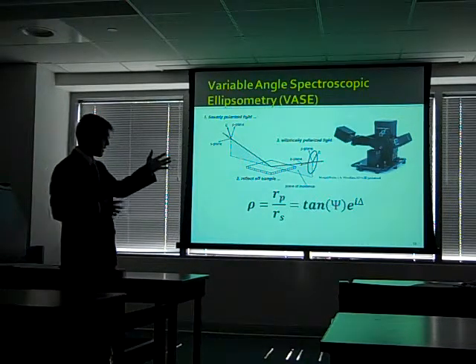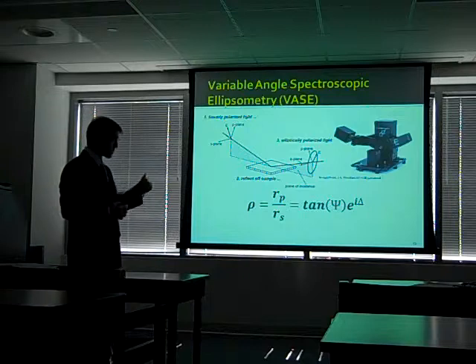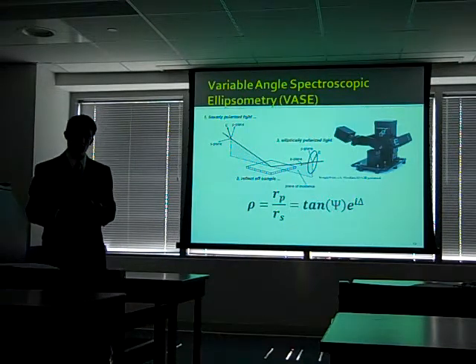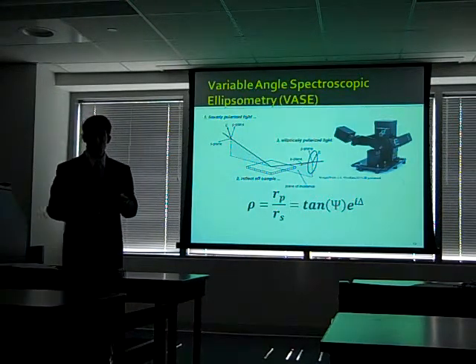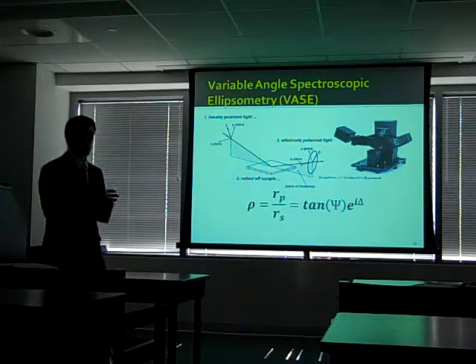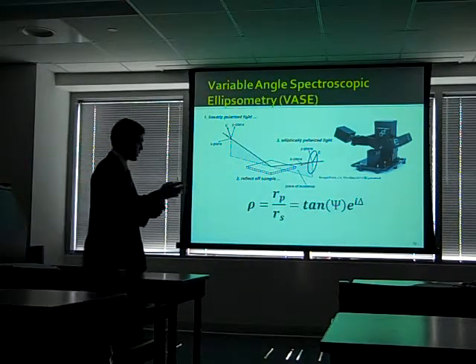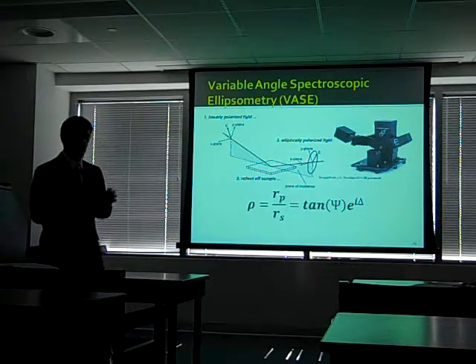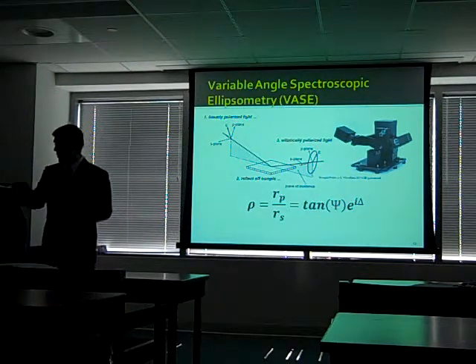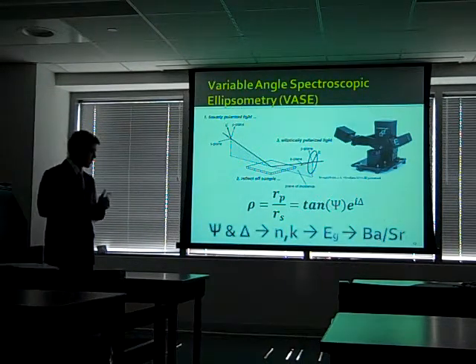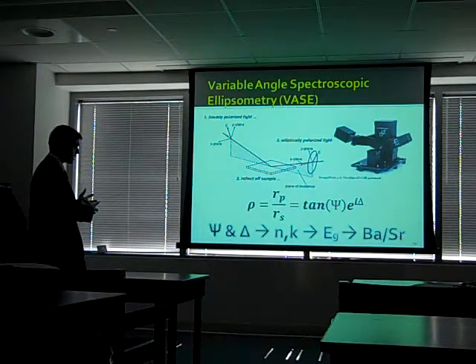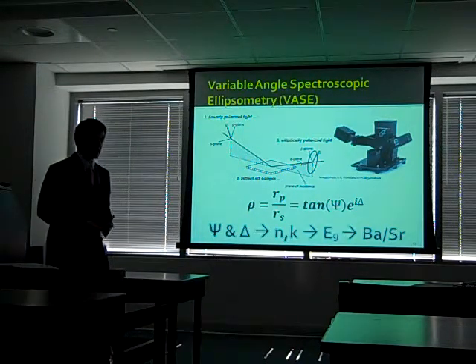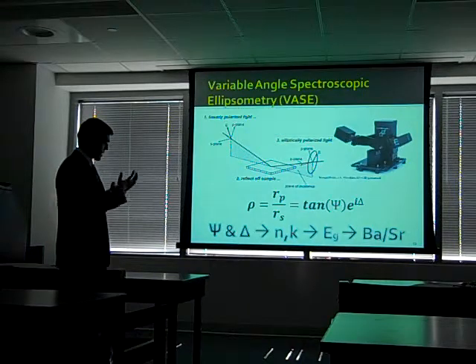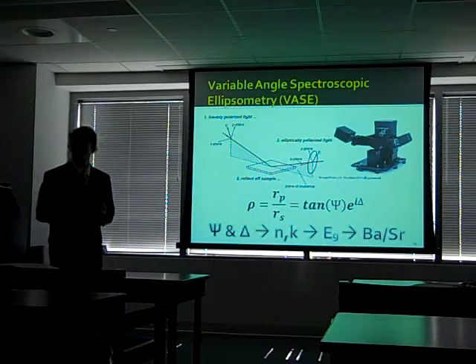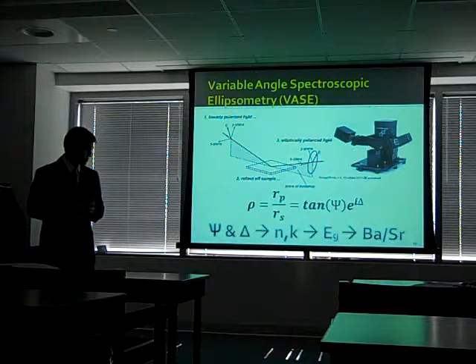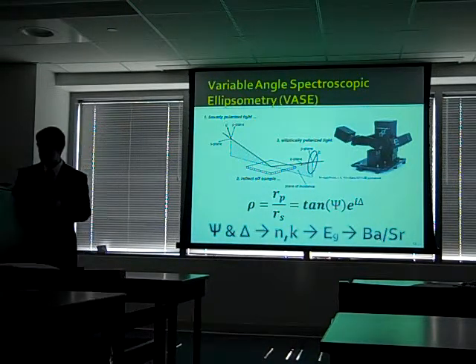So from that information, the ellipsometer can give you psi and delta, which are the ellipsometric parameters. Psi is the ratio of the magnitudes of the p- and s-polarized components of the light, and delta is the phase difference between the p- and s-polarized components. So through Snell's law and Fresnel equations, we can relate psi and delta to optical constants like index of refraction and extinction coefficient. And then from there we can extrapolate band gap and determine the barium to strontium ratio if it's in the perovskite phase.